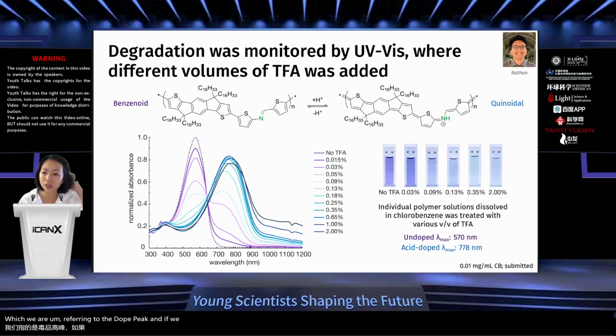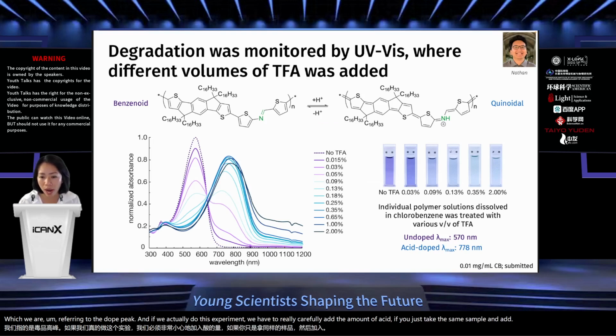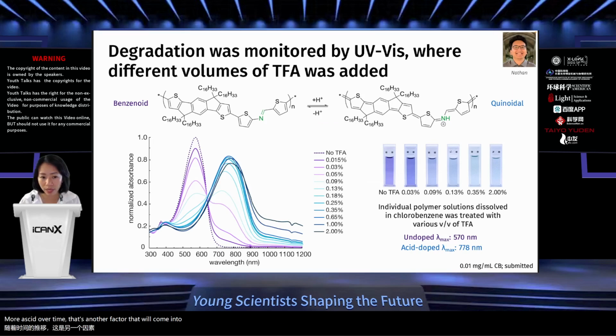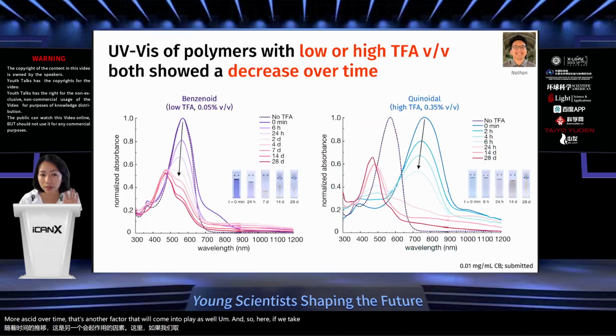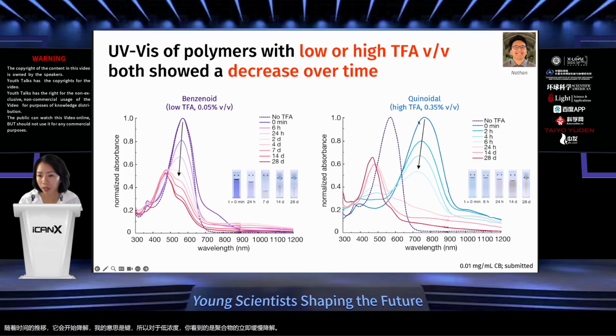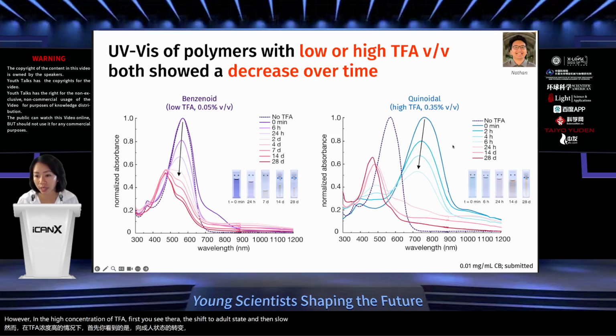And if we actually do this experiment, we have to really carefully add the amount of acid. If you just take the same sample and add more acid over time, that's another factor that will come into play as well. And so here, if we take the same concentration of acid on the sample and just monitor it over time, we can actually see the decrease of the UV vis. And this decrease is expected because as the polymer is sitting there over time, it will start degrading the imine bond. So for low concentrations, what you see is an immediate slow degradation of the polymer. However, in the high concentration of TFA, first you see the drastic shift to a dope state and then slow decrease over days right here. You can see really nice colors associated with this color change as well.